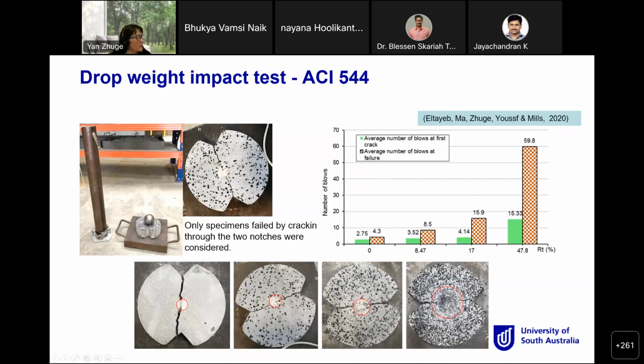Yeah, okay. So we did some drop weight impact testing based on ACI 544. You can see for this testing, each disc had a diameter of 150 mm, as shown in the diagram, and the thickness was 50 mm. A steel cylinder was repeatedly dropped from a vertical height of about 200 millimeters, 20 centimeters, through a hollow steel tube. The total number of blows required to split the concrete specimen into two separate halves was recorded. So that is the result.